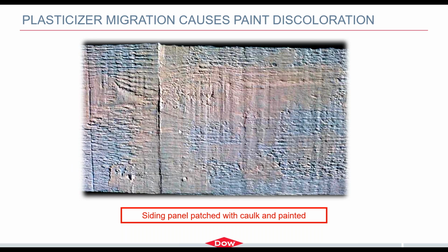Another larger example of plasticizer migration is with this siding panel that somebody took some sealant and decided to use it as a patch. So they took the sealant and they smeared it over the side of the panel to make it more uniform looking, and then they painted over it with this light blue paint. As you can see, due to plasticizer migration to the surface, you now have all these lighter whitish spots, and you have this whole mottled surface.